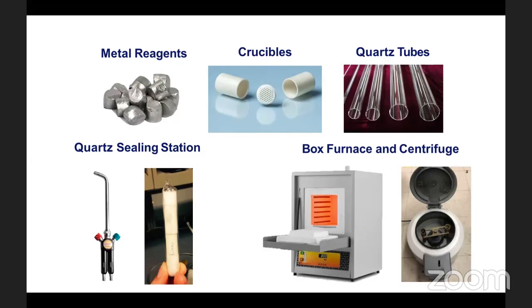For the flux growth technique, you need a material and you need a container, and you have to seal it. Once you seal it, you keep it in a furnace, let's say at 1000 degree for your material. Keep the material for 2 days, then slowly cool down to around 600 based on your flux material. Mostly more than 200 degree, you keep at 200 degree temperature while cooling down. In that temperature, this is a very tricky process. You take the container and put it in a centrifuge and rotate it very fast, only 1 minute. If you rotate it, you will get crystal separate and flux separate.